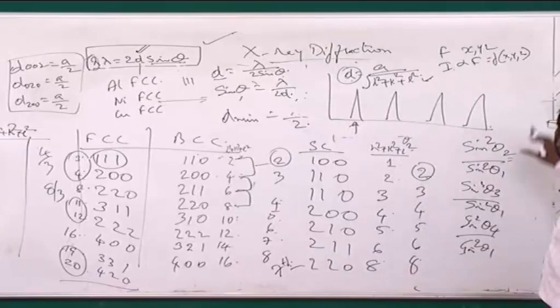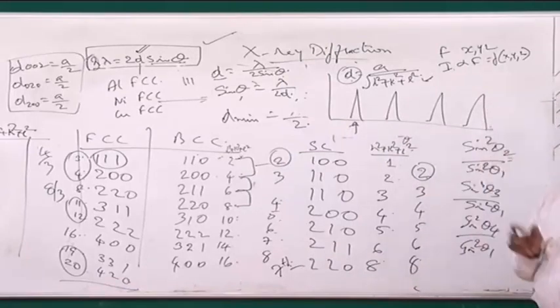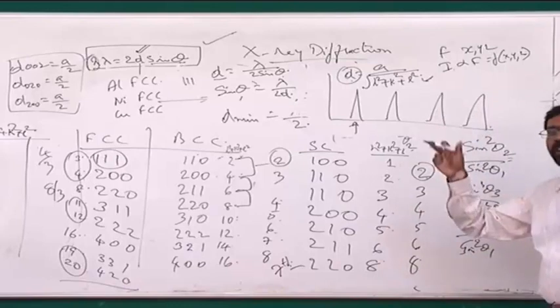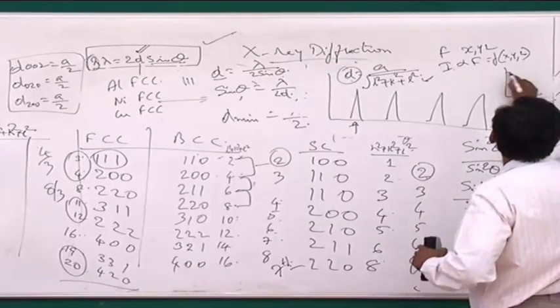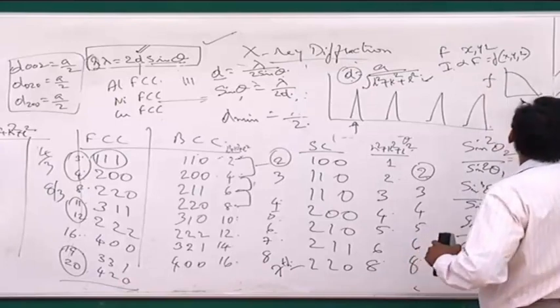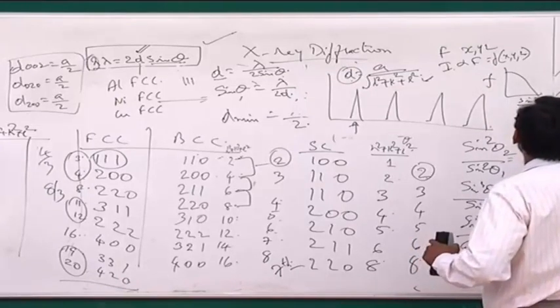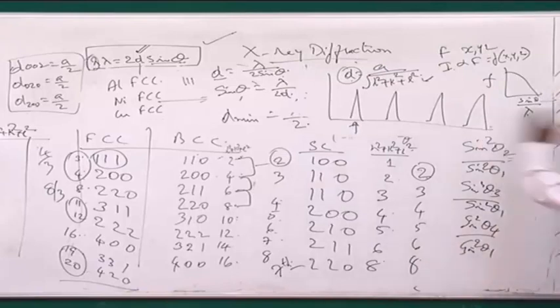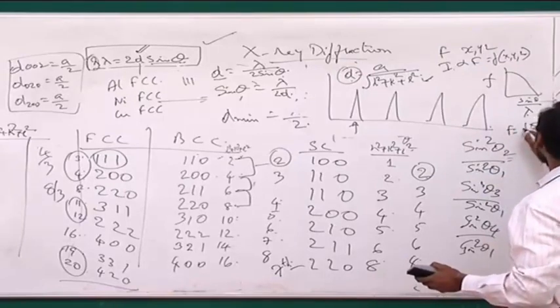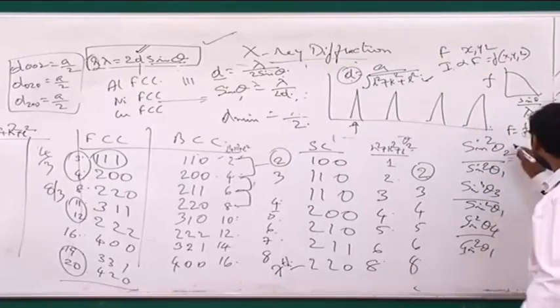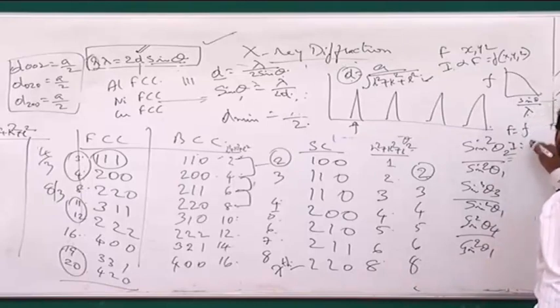And those are the ones which will have smaller intensities, because we said earlier that small f is inversely proportional to sin theta by lambda. We showed that this is a relation between small f and sin theta by lambda. As the theta increases, the f decreases. And I have seen that capital F is related to small f, and I is related to capital F square of it.